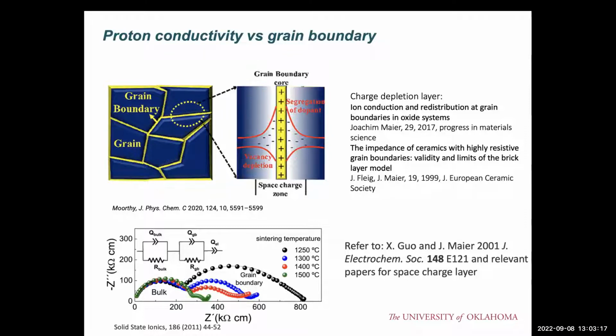For the electrolyte material, we need to densify the electrolyte, right? And we densify the electrolyte because we want to achieve high conductivity. In the proton conducting electrolyte, we want to achieve high proton conductivity. But in reality, the conductivity can be limited by the grain boundary, because between two different grains there is a depletion layer of oxygen vacancies, which is positively charged. This depletion layer is called the space charge layer. This layer can limit the transport of the oxygen ions and also the protons. Eventually, it can reduce the overall conductivity of the electrolyte materials.